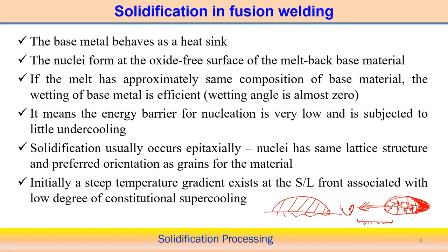So starting with this, the nucleation starts with almost zero wetting angle, or I can say almost no energy barrier, and at the same time the degree of constitutional supercooling is also very low. So in this particular situation, solidification starts at the trailing edge and usually occurs epitaxially. Epitaxially means that the nucleus has the same lattice structure and preferred orientation of the grain in one particular direction.